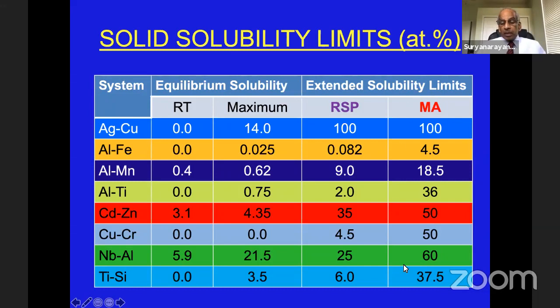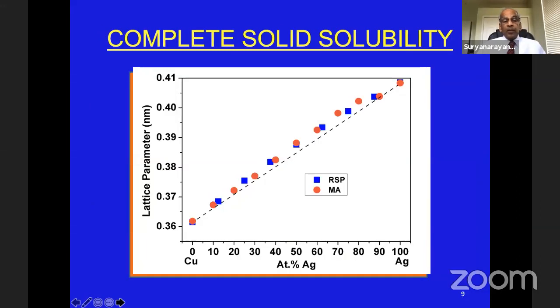So I've chosen a few typical examples, but not everything. Now, how do we understand the formation of these supersaturated solid solutions here? If you look at the silver copper system, these are the lattice parameter values obtained by mechanical alloying, and these are the values obtained by rapid solidification.